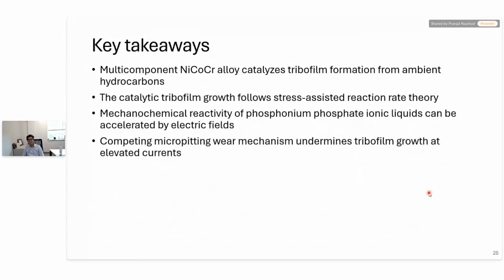So to conclude my talk, we discovered that a multi-component nickel-cobalt-chrome alloy can catalyze carbon-based tribofilm formation from ambient hydrocarbons, the hydrocarbons in air. The growth of these tribofilms follows the stress-assisted thermal activation model. So the film growth is promoted by both stresses and temperatures. We also studied the mechanochemistry of phosphonium phosphate ionic liquids under electric field, and we discovered that electric fields enhance tribofilm growth. And we propose a new kinetic model that captures the reactivity of additives under electric fields. We discovered that there is a competition between mechanochemical reactions and micropitting wear. And at very high currents, the micropitting wear dominates and undermines mechanochemical reactions.